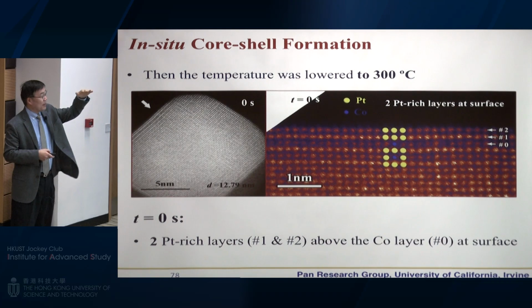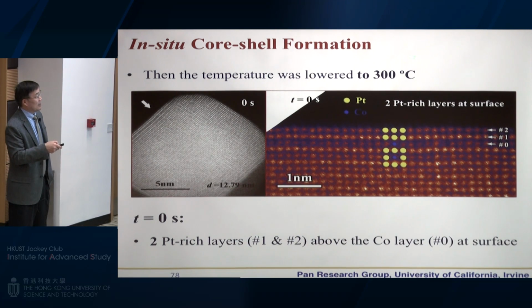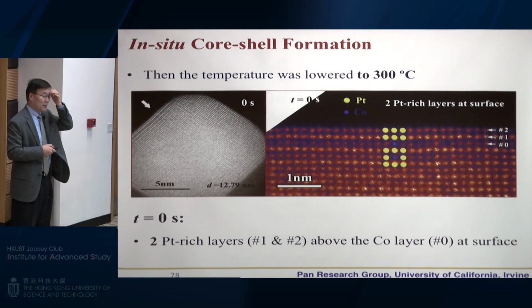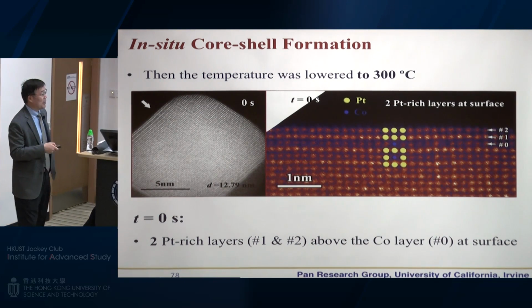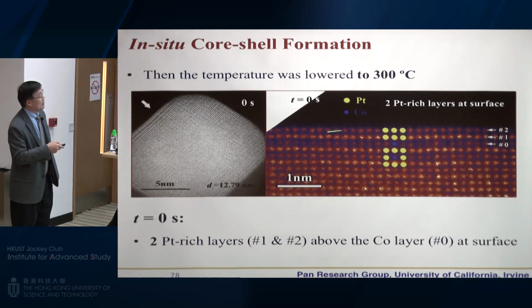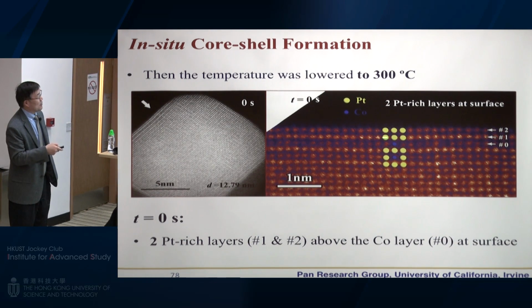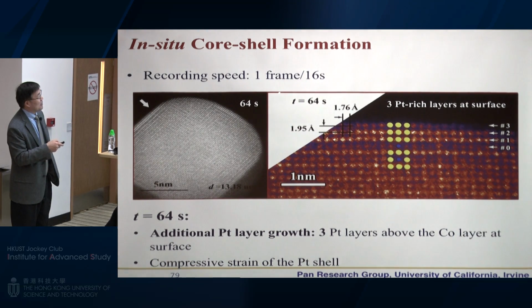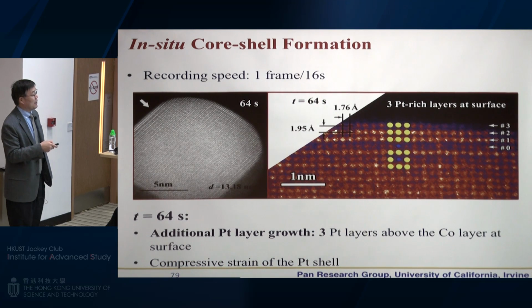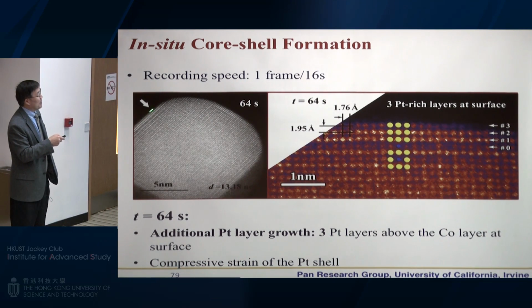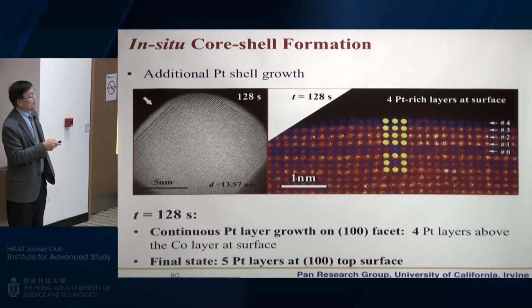just lower the temperature to 300 degrees C. Then you can gradually see the formation of more platinum shell on this ordered particle. Initially we see 2 layers already. Then after 64 seconds, 1 minute later, you can see that this becomes 3 platinum layers. Then another minute, and you can see 4 layers on the surface.